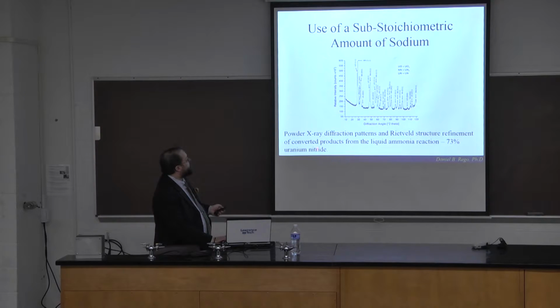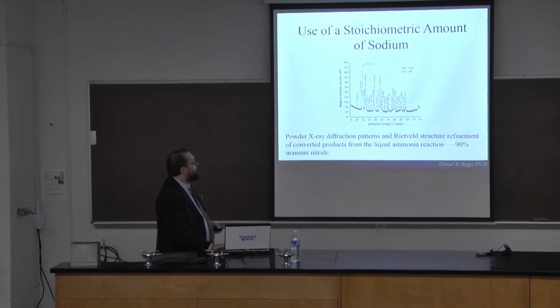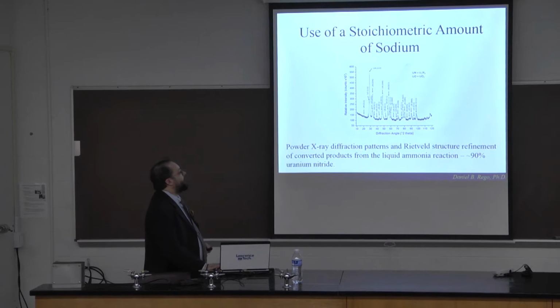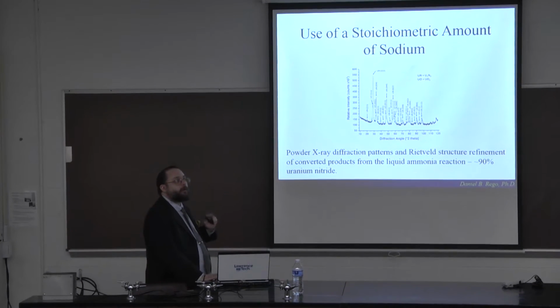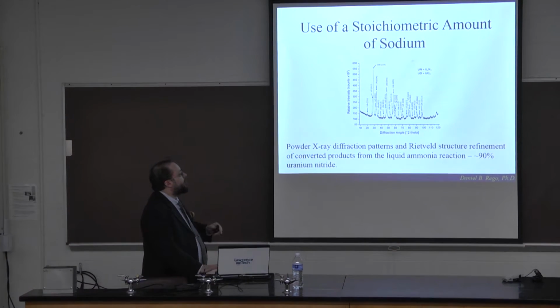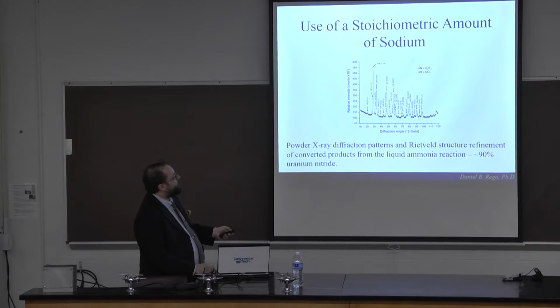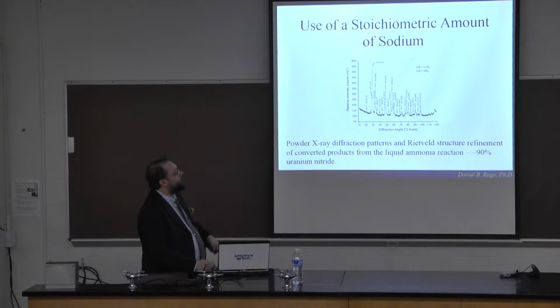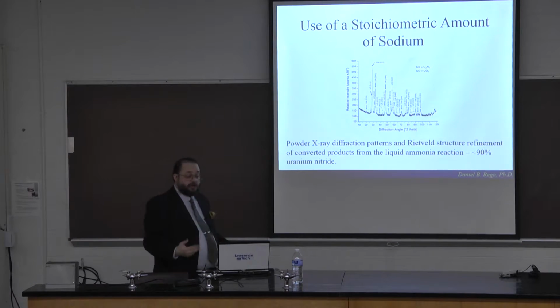The interesting thing is that when I add a small amount of sodium metal to the ammonia, sodium metal being fully dissolvable in ammonia, I end up getting 73% uranium nitride. Add more, and I can get 90% uranium nitride. So just a small matter of adding sodium completely increases the yield from pretty much nothing to about 90% without changing anything else.